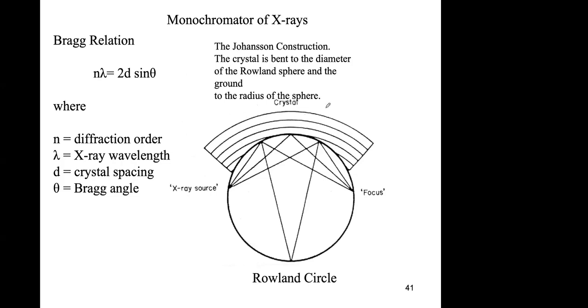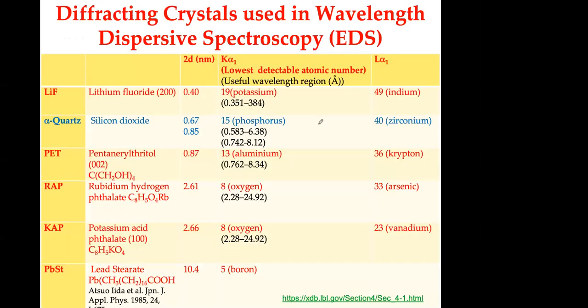It's not one crystal, so it's a number of crystals. There are different crystals that can be used. This is a table of crystals that are used for wavelength dispersive spectroscopy for X-ray fluorescence. Depending on the crystal is the range of energies, or lambda, that you can detect. For example, if you use lithium fluoride, it can go from potassium to indium with good resolution.